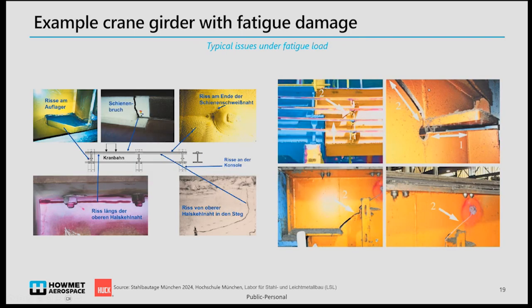That sounds probably very promising, but this is not just a marketing value. We have seen our fasteners resulting in very high fatigue resistance also in some research projects. Here are a few examples of failures for welded connections. We see, for example, cracks on the support structures or some cracks originating in the throat fillet weld and at the end of the rail weld. But due to these cracks, basically the structures cannot be used anymore.